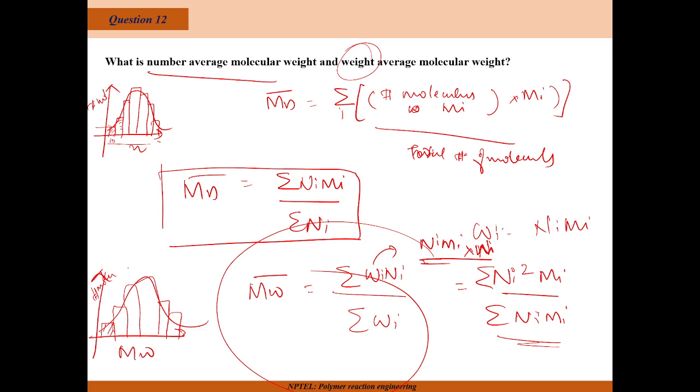Okay, fine. I had a doubt because for GPC, we get both Mw and Mn, and that will directly give the polydispersity index by measuring Mw and Mn. Whereas in vapor pressure osmometry, generally we go with the number average only, since it is a colligative property we directly get. So that's why I had a doubt.